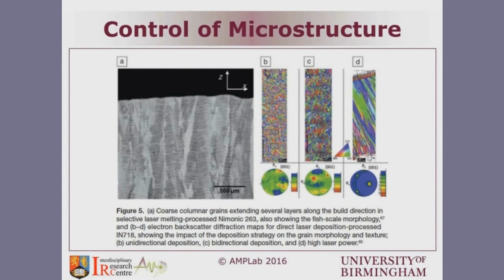But we can still, by changing one parameter, like in the case of B and C, change the scanning strategy from unidirectional to bidirectional scanning. We can see that we can grow the grain size a little bit. And if we increase the energy, the laser power, we can end up getting epitaxially grown grains from the bottom to the top with fairly columnar grains.